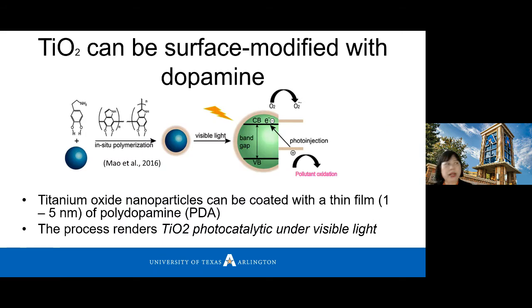So let me continue with our strategy. The titanium oxide can be surface modified with dopamine, using in situ polymerization. When visible light stimulates this coating, it will produce reactive oxygen species. From these reactive oxygen species, it can kill the bacteria and the virus, and it will facilitate the titanium oxide photocatalysis under visible light.